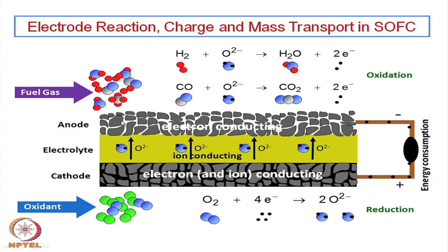Both the cathode and the anode material have to be porous, whereas the electrolyte has to be a completely dense material, because some such material is already available with us, like zirconium dioxide. We have seen earlier calcium stabilized or yttria stabilized zirconium dioxide can act as a very good oxygen ion conductor, and therefore, these are the materials one can use. We will come to what are the different materials possible to use either as a cathode material or the anode material. In case of carbon monoxide, a very similar reaction takes place. Instead of hydrogen, one can have carbon monoxide and then oxygen ion gives carbon dioxide. So, it again releases two electrons here.